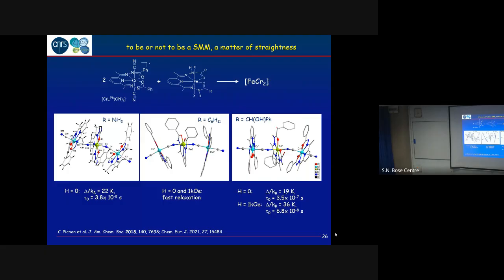One shell is filled, but there is no anisotropy. Actually, there is no anisotropy because if you put your 3 electrons in the energy diagram I have shown before, you have 1 electron per orbital. So this is not a good situation to get a large anisotropy because to go to an excited state, the energy difference with the orbital you are going to populate is very large. So if the energy difference is large, the contribution to anisotropy is very small.